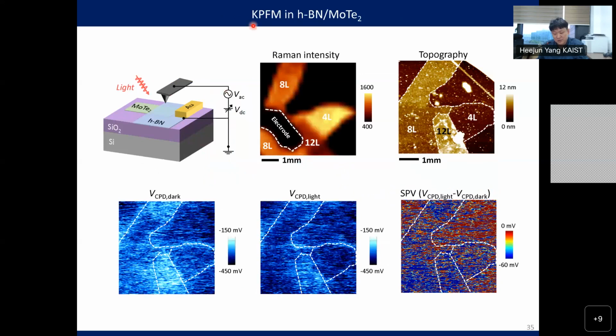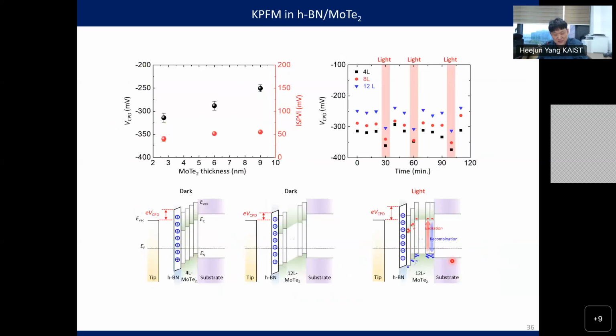So some of you maybe know Kelvin probe force microscopy, and maybe many of you are doing this technique as well. But one unique thing in our group is we illuminate light during this measurement. So we measure the surface potential under the light or in the dark condition, and we compare this quasi-Fermi level or the quasi-surface potential.